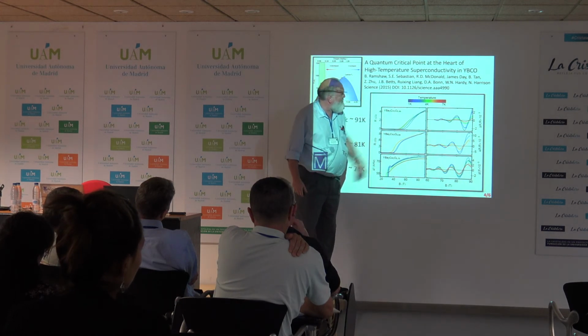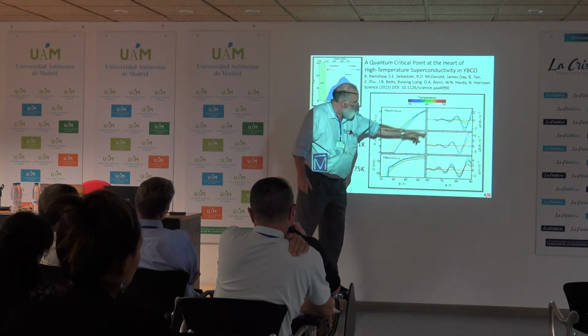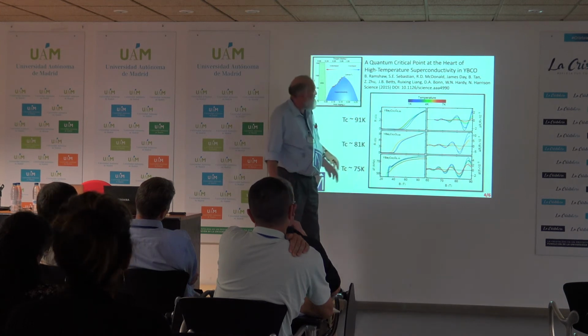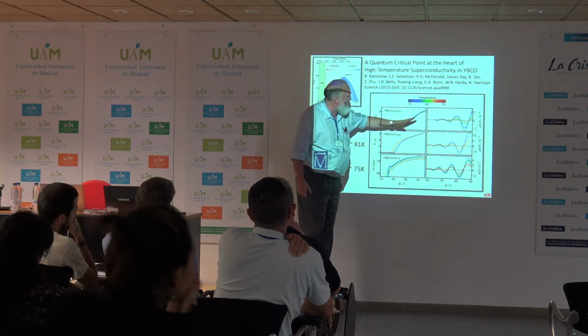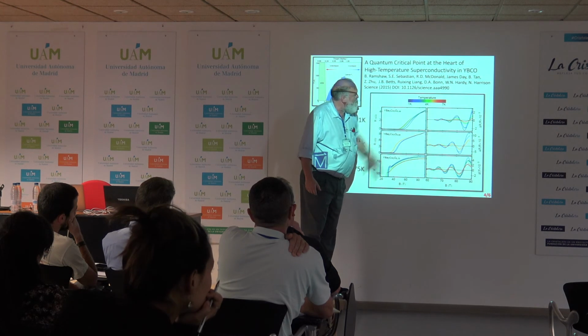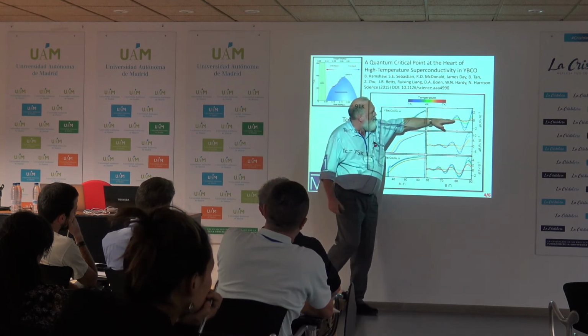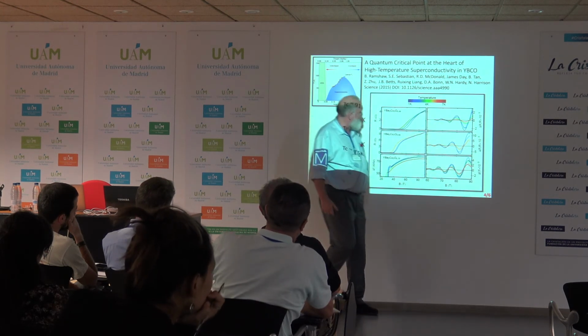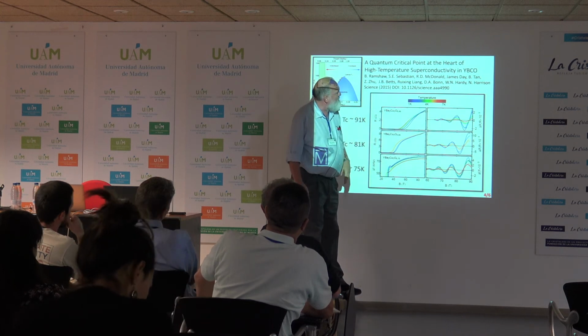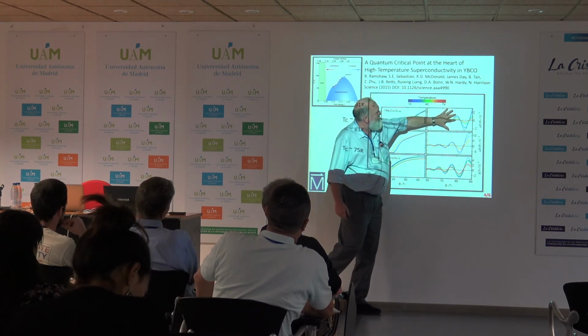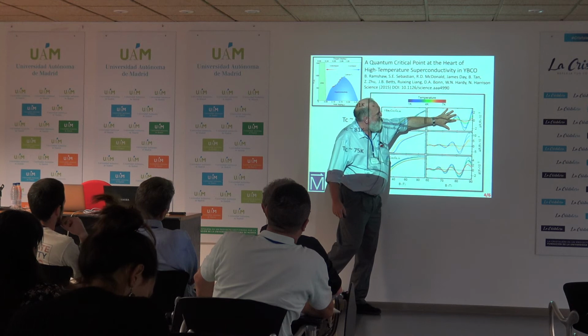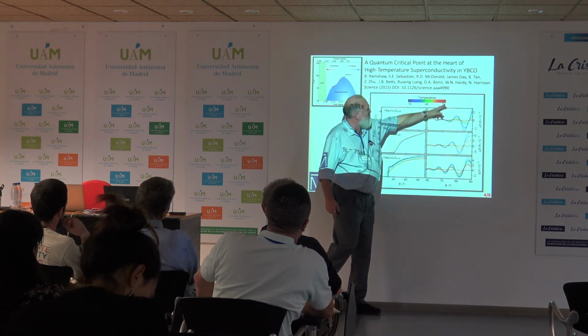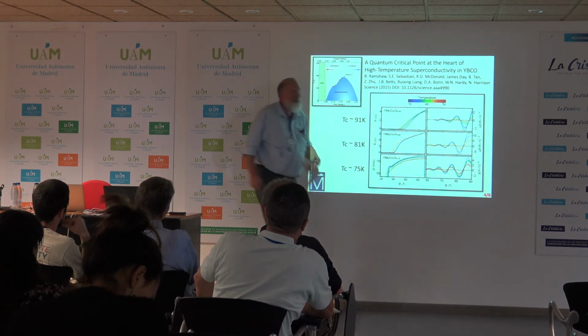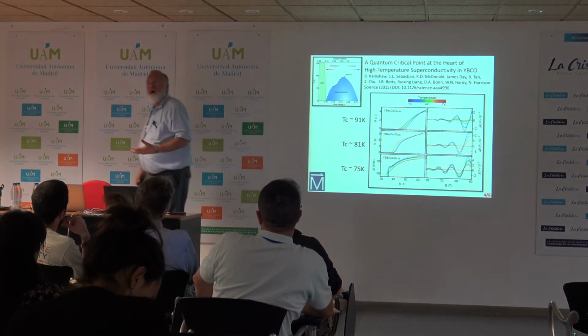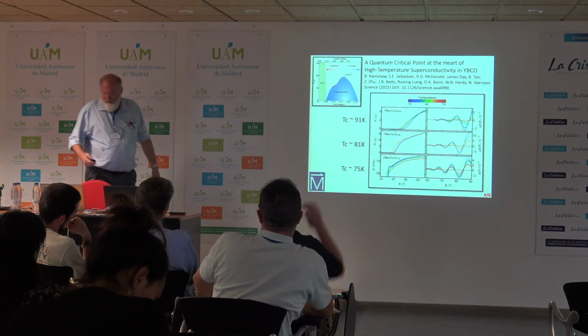I'm sure you can all see them here in the data. I'm only poking fun at Brad because he's a good friend. This is incredibly good data. And they just subtract a smooth background, and you see very clear oscillations in each of these three data sets for three different dopings. And they measure the temperature dependence. It's largest at low temperatures, smallest at high temperatures, from 1 to 7 Kelvin. And from that, they can deduce a mass of the quasiparticles for that doping.